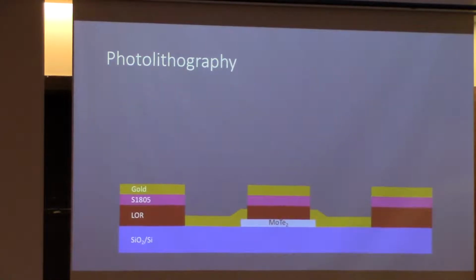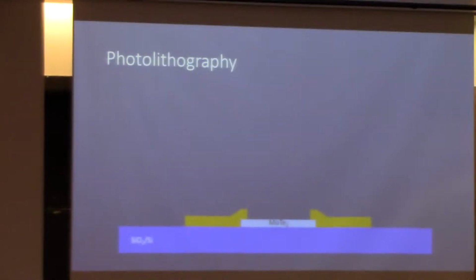Then I can thermally deposit gold all over my substrate. I can put this in a different chemical that dissolves away the rest of the photoresist. The gold I don't want floats away, and I'm left with some contacts that can start at my flake and head out to some big wide square that I can actually stick a wire to now.